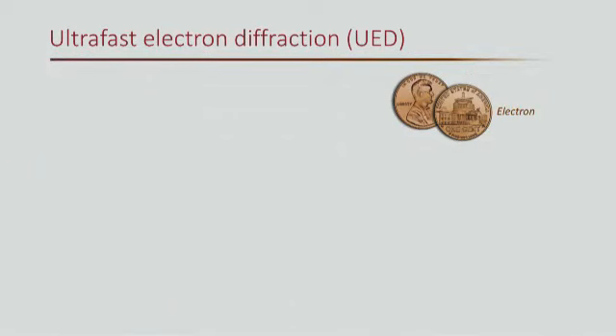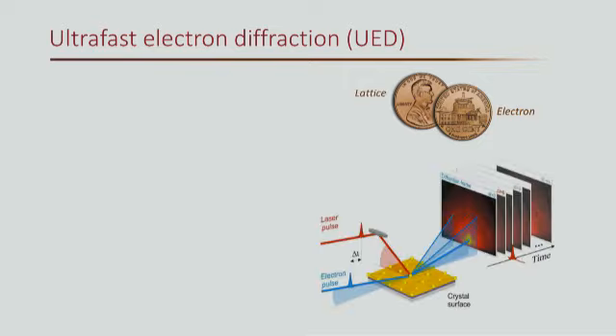So we see that time-resolved TARPES can give us information about, for example, how the electronic band structure changes. Of course, the other side of the coin is how the lattice changes. And in this case, we use the so-called ultrafast electron diffraction. Essentially, it is electron diffraction, but we take a diffraction image at every instant of time after the pump pulse arrival on the sample. So basically, this is a schematic diagram where we generate the electron pulse by putting UV light onto a photocathode, where we generate an electron bunch through the photoemission process.